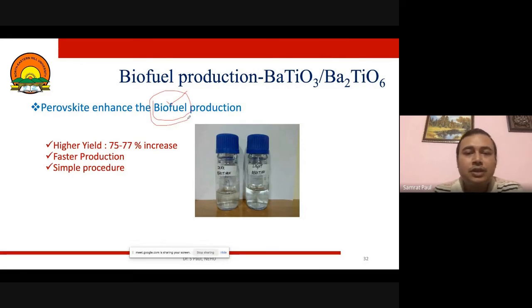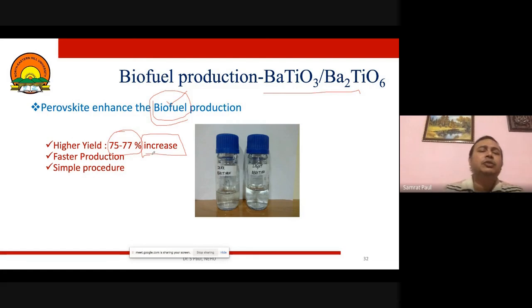The work has stopped because of COVID. This is just a two-year-back result. Though we have communicated this to one journal, the initial results have been published in the form of a letter. One more advantage is that the conversion efficiency using this type of heterogeneous catalyst is very high. The higher yield means about a 75 to 77% increase in yield can be recorded with respect to KOH or NaOH based catalyst use.